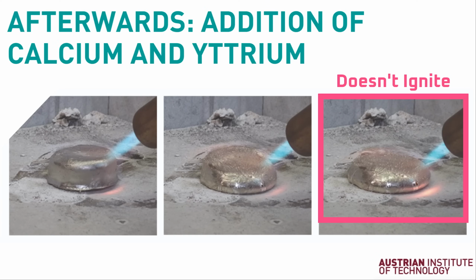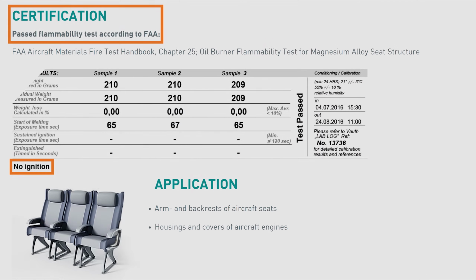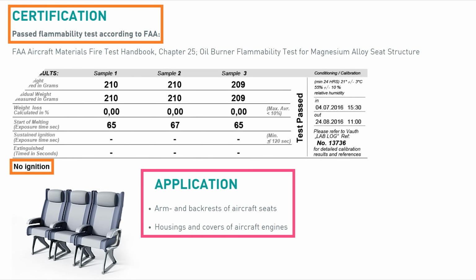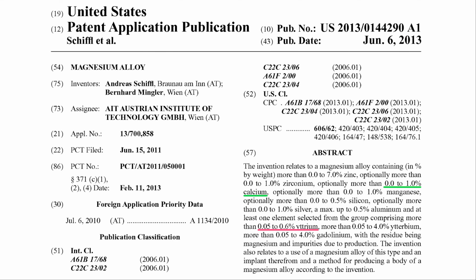More recent advances in fire-resistant alloys from the Austrian Institute of Technology, or AIT, show that the addition of calcium and yttrium allow magnesium to be heated to its molten state and it doesn't ignite. That was confirmed in testing by the Federal Aviation Administration, and the alloy has been approved for use in jets. It's not clear how much calcium and yttrium AIT used to achieve that result, but their patent application indicates that it's likely between 0 to 1% calcium and 0.05 to 0.6% yttrium, so the dopants only made up a fraction of the alloy.